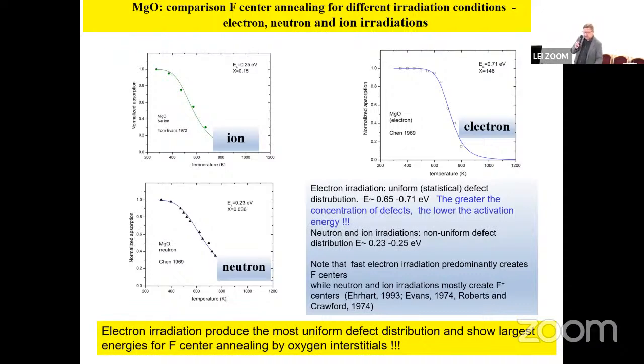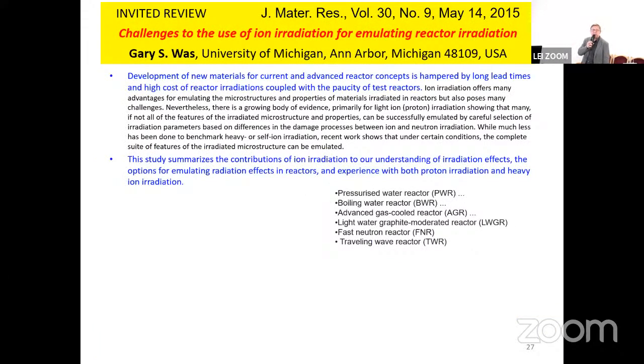But when we started this activity, we understood that all the data existing in the literature were obtained on different samples. If we are talking about a defect concentration of 10 to the 19 per cubic centimeter, very often this is on the same level as the dopant concentration, because there is no pure single crystal. There are always some dopants, even if you check all the companies which are producing them. So many years ago, people started to use swift heavy ion radiation to emulate neutrons because of the quite similar defect behavior.